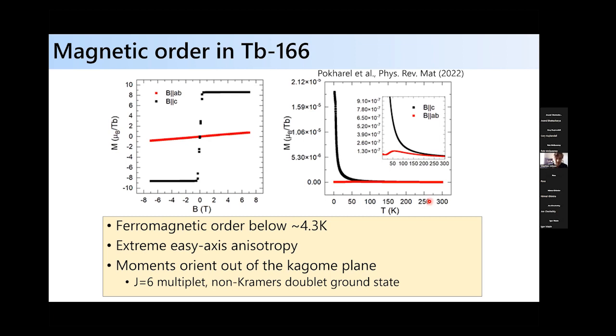And the magnetic order that's realized in this system, if you look at low temperature, in the ordered state, you can see it's a strong easy axis anisotropy with the moments pointing along the z-axis. So that's out of the Kagome plane. And you can see the effect of the field pointing along c and a very strong anisotropy versus when you put the field in the ab plane. Okay, and so you can start to see hints of this in the magnetization, but there's a low-lying crystal field excitation out of this doublet ground state. Basically the terbium 3+ is a J equal to 6 multiplet. And so the first excited state, you can start to see hints of that being populated when you warm near 50 Kelvin.